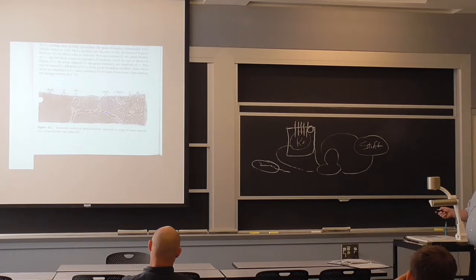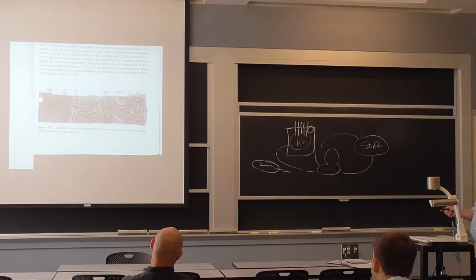You get over here to even higher concentrations, and all of a sudden these gamma prime precipitates start to become kind of square rather than round. And there's good crystallographic reasons for that. And you get to volume fractions of the gamma prime phase that can be 85% intermetallic, surrounded by some solid solution. And that's what gives you the really good strength, okay, at high temperatures. But you can also get nodules and stuff, and you have to process it, and you have to forge them if they're not cast, like some of the turbine discs. You have to forge them the right way to break up some of these original solidification structures.